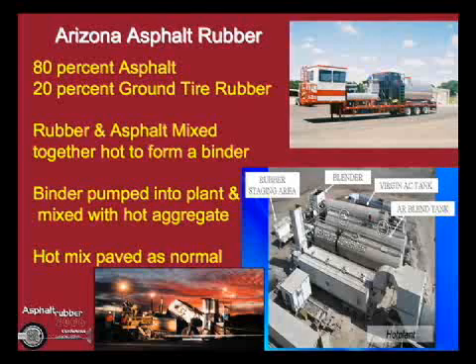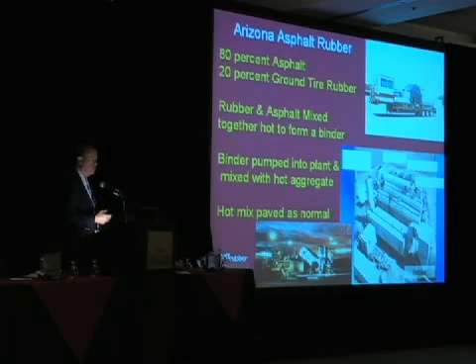It's roughly about 20% ground tire rubber and 80% asphalt. And normally in Arizona, we use about 1 or 2 grades softer asphalt than would normally be used for the PG grading. So the PG grade in Phoenix is about a 70-10 or 76-10 or 76-16. We use a 64-16 for the base asphalt for asphalt rubber in Phoenix. And in Flagstaff, a high cold temperature area, we use about a 58-22. And those work very well as the base asphalts.